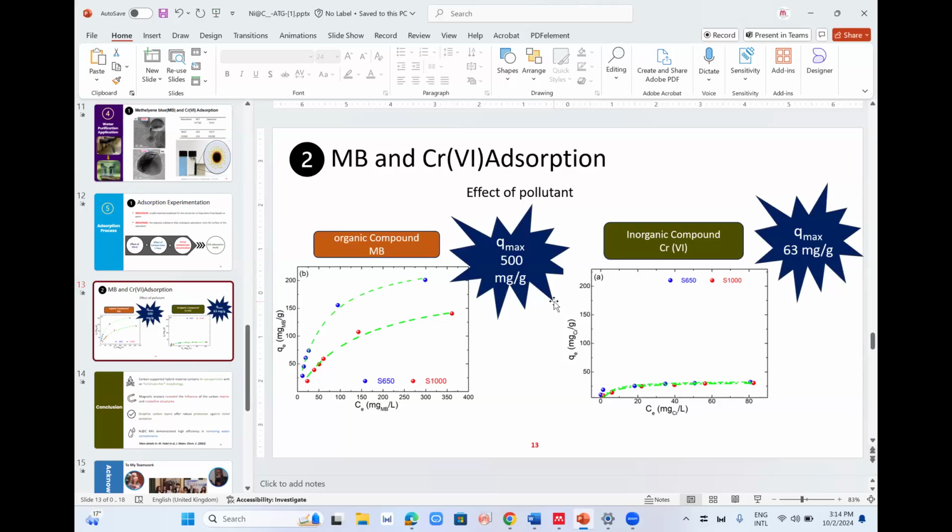The area of porosity is not related to nickel, it's related to the graphite layer and turbostratic carbon. The nickel just helps me so that after adsorbing the contaminant, I can separate the nickel and the carbon magnetically. So the idea is magnetic with carbon.